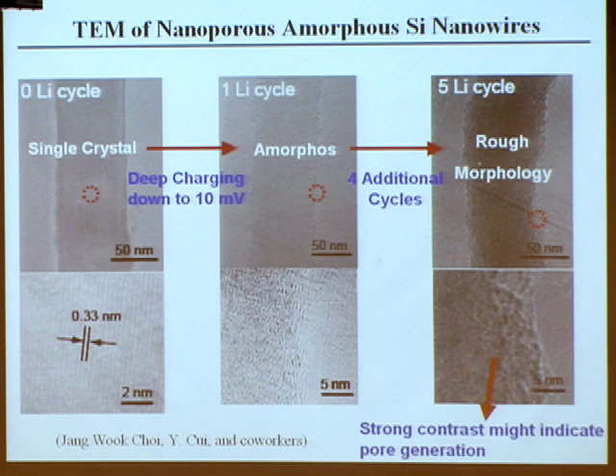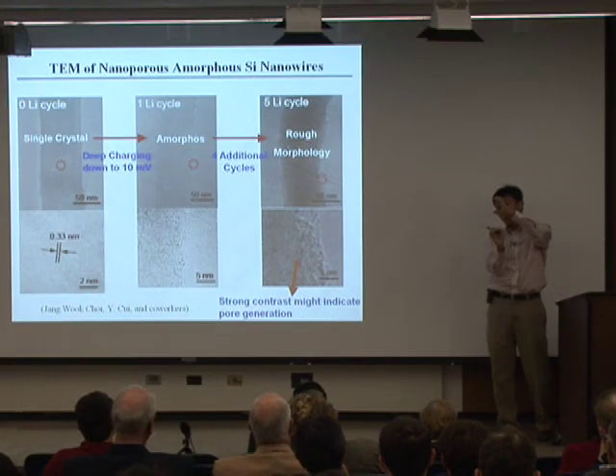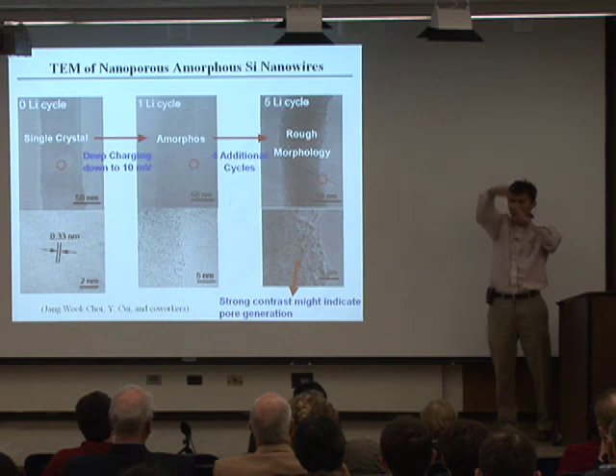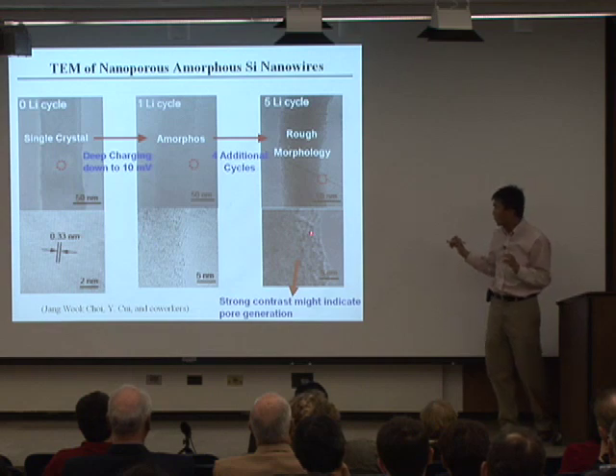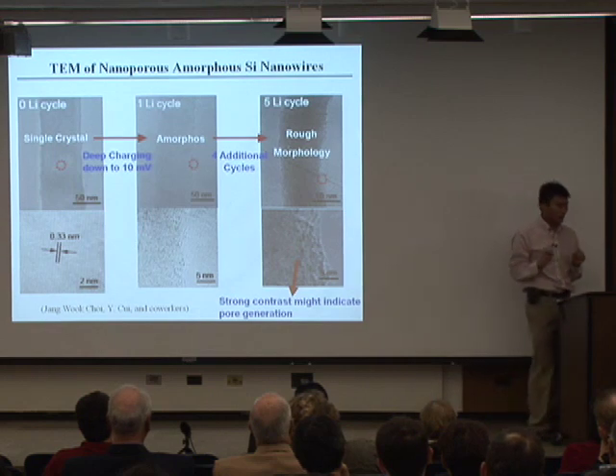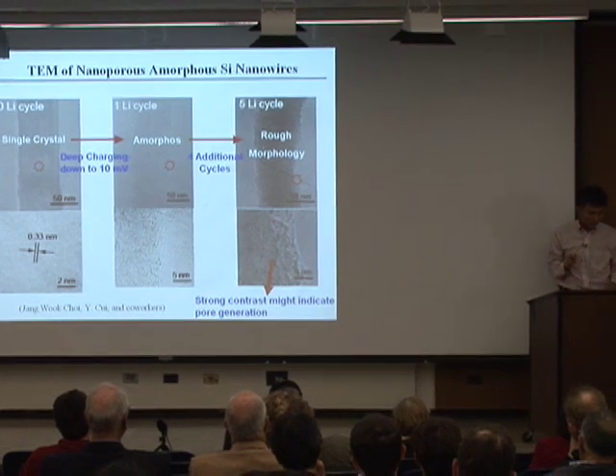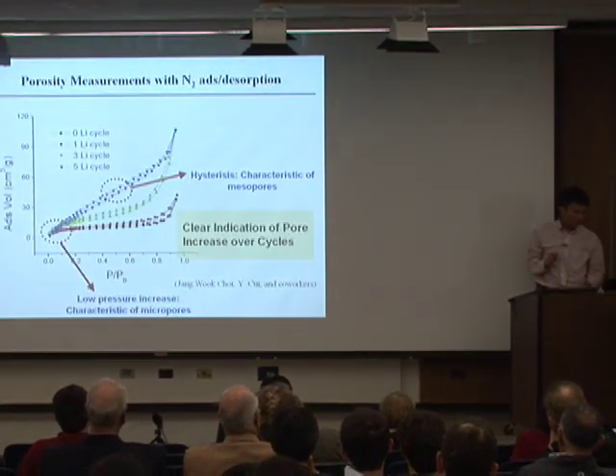But after 5 lithium-ion cycling, you see the roughness becomes more. Well, this allows you to believe maybe there are really pores inside, but you cannot resolve them clearly because you have a lot of pores. Your electron beam coming down goes through so many pores. So this averages out, but more or less the roughness becomes larger. So this gives you some indication. You might have nanopores right there.